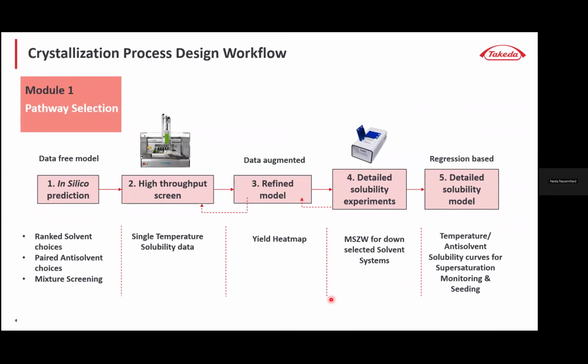So here is module 1, pathway selection. Again, this is in early development. We never have perfect data or a lot of samples to measure a lot of solubility. That is exactly why we need a staged workflow. We start with a data-free or very low-data model to rank the solvents and identify promising solvent-antisolvent pairs. Then we run a focused high-throughput screening, not a broad empirical sweep, and this gives us enough information to refine the model and generate some yield maps. After that, we invest in more detailed solubility and metastable zone work only for the down-selected systems. So instead of measuring everything everywhere, we sequence the learning. And every measurement, every experiment would be used for refining and having a better model for solubility predictions.